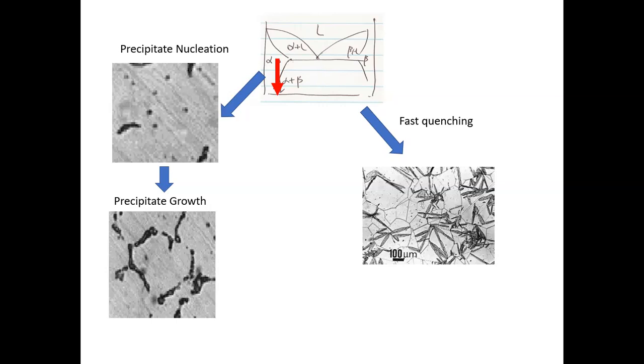Now, however, they're very, very unhappy about this, right? Because they're getting stuck in this high energy state where they can't reach a lower energy. So they're very unhappy about that. But there's nothing they can do through diffusion, because you already cooled the system to a very low temperature. The atoms are not moving around at that low temperature. But nature is very smart. It invents or adapts another pathway to lower the free energy, not to the best that it can, but still lower the free energy a little bit, through a spontaneous, I would not say spontaneous, a global, fast transformation that involves the change of the entire crystal structure. Okay, so this is the martensite transformation.